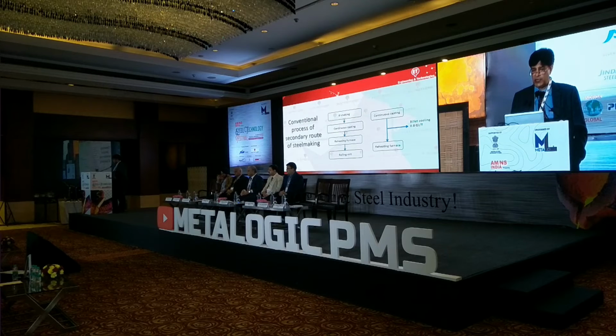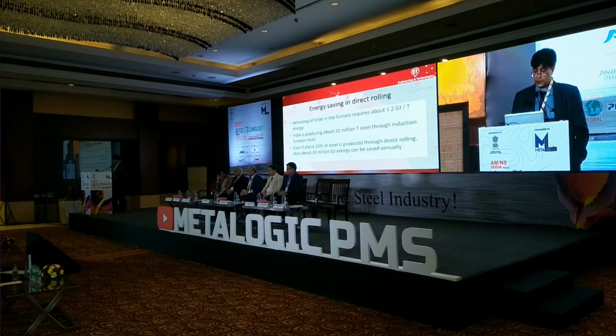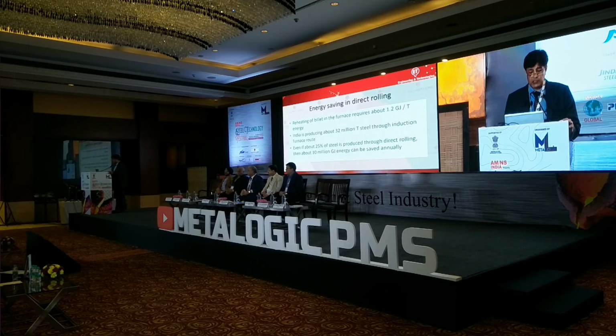When the billet is cooled, you are losing about 0.8 gigajoules per ton of energy. Now, reheating the billet in the furnace requires almost 1.2 gigajoules per ton of energy. India is producing almost 32 million tons through the induction furnace route. So even if 25% of the steel is produced through direct rolling, then about 10 million gigajoules of energy can be saved annually. This is huge.